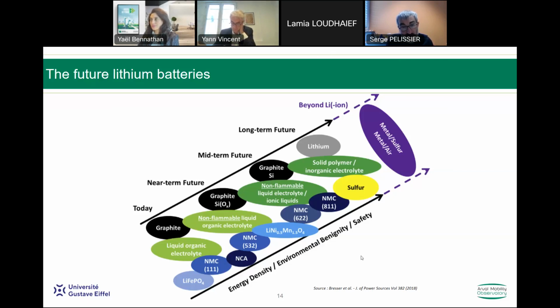This lithium metal associated with a solid polymer as an electrolyte will ensure higher energy density, higher safety, and longer lifetime. But the problem at present is that this solid polymer electrolyte needs a high working temperature, around 80 degrees. So lots of research is presently being done to try to decrease the working temperature of this type of materials. Next slide, please.